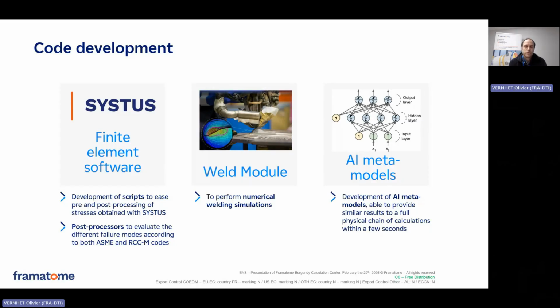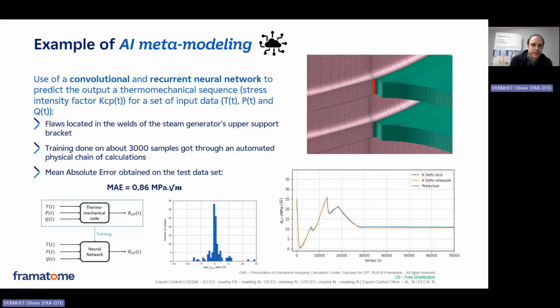we tried to check whether it was interesting or not to use some artificial intelligence meta models. So we developed some meta models that are able to model the full chain of calculations I showed you at the beginning of the presentation, going from the loadings until the criteria for fast fracture, fatigue, and so on. And so we showed that we could develop a meta model that is able to calculate stress intensity factor without going through SYSTUS, without going through the post-processors, only using AI meta models. And I'm going to present you the results that we had.